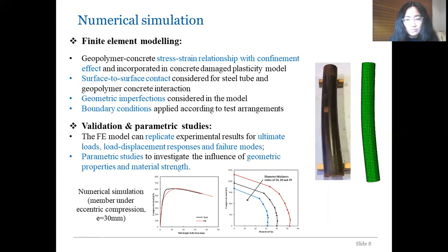So just to show one set of results from the parametric studies in the plots shown in the middle. It's the results for the members with the steel tube with a varying diameter to thickness ratio. And it shows that the structures with lower diameter to thickness ratios for the steel tube provide higher resistance to the combined compression and bending, as the red color curve.